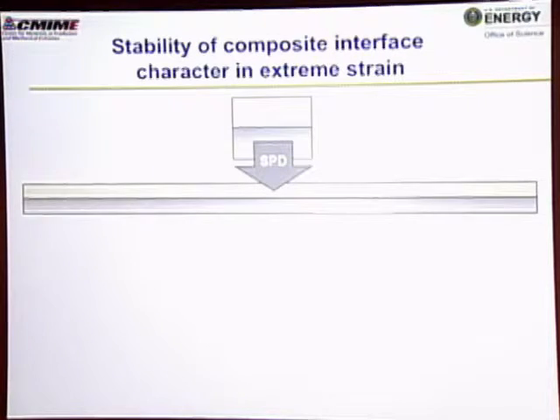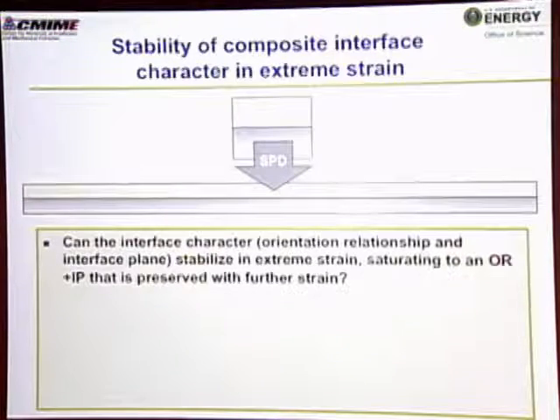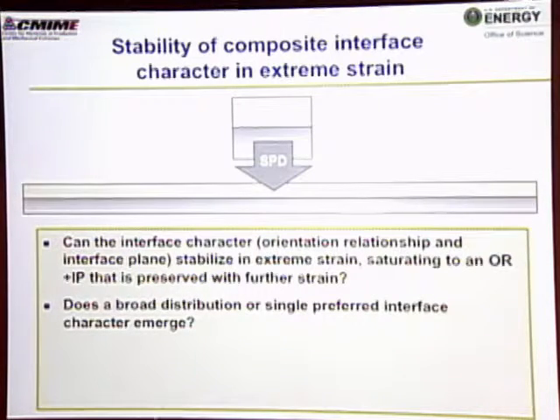So what happens when we do this? If we take our material, copper, niobium in some cases here, and we roll them by severe plastic deformation technique, we roll them out very, very far, what we find is that we can ask some questions. Can the interface character stabilize in extreme strain, giving you a certain type of interface that's preserved with further strain? Do you get a broad distribution, like if you were just to roll copper or niobium alone? Or do you get a single preferred interface, like you see in physical vapor deposition?